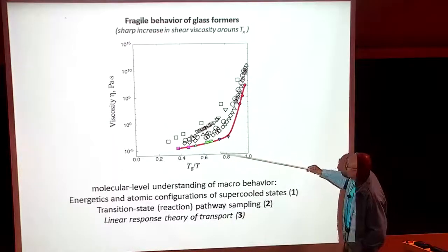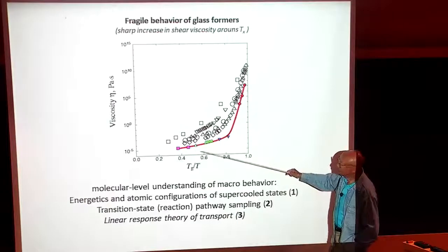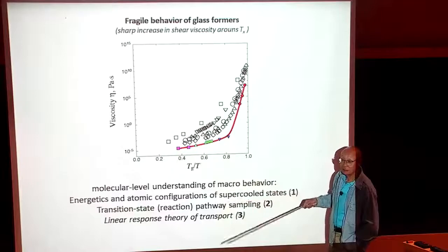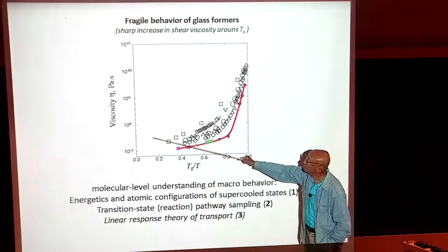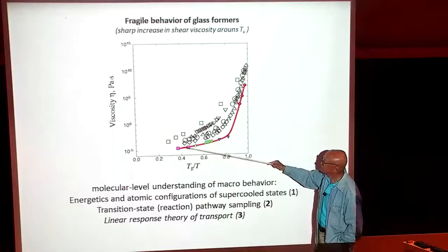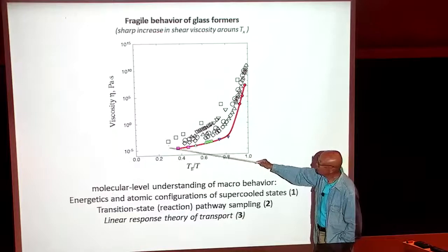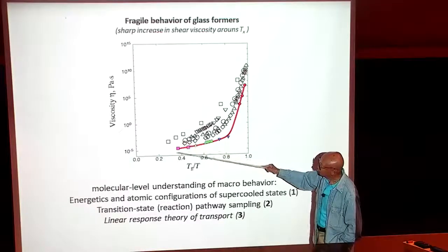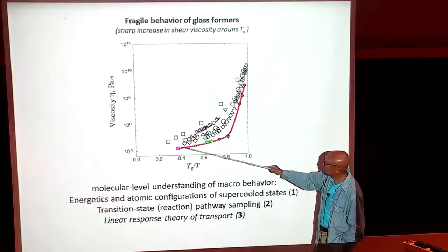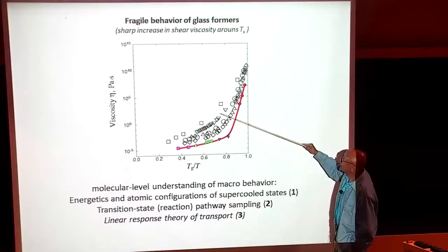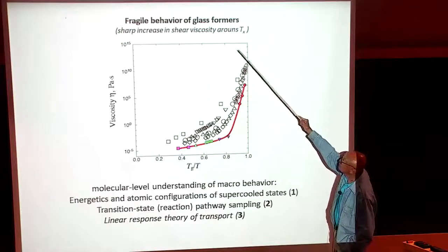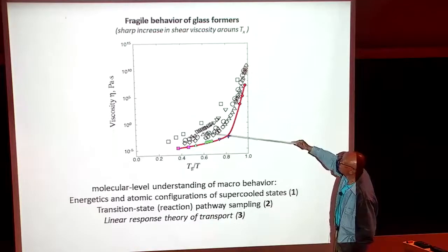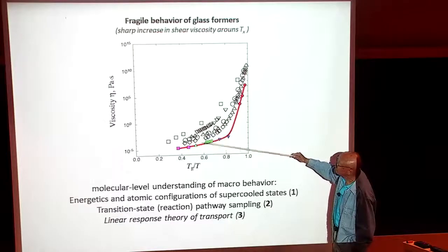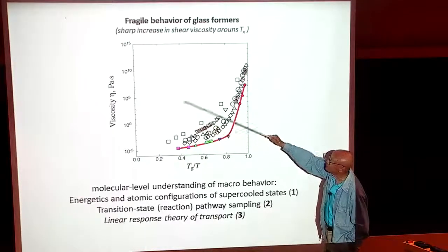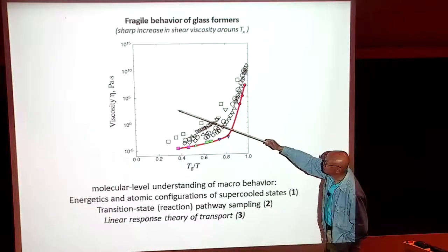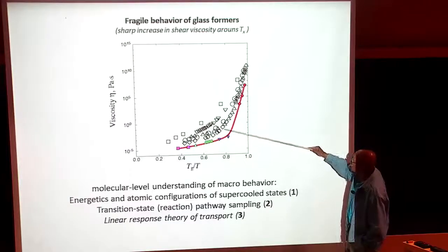So as you go to lower temperature, you're actually moving to the right. The room temperature viscosity of, say, water, 10 to the minus 2 poise, is down here. It's very low. This is a low viscosity regime, a high temperature regime, 1 over the temperature now. And then as you quench the system down, it doesn't crystallize, it's vitrified, so at some point it turns into what you call a glass. We can talk about other properties of this vitrified liquid, but if you just measure viscosity, it shows very dramatic behavior.